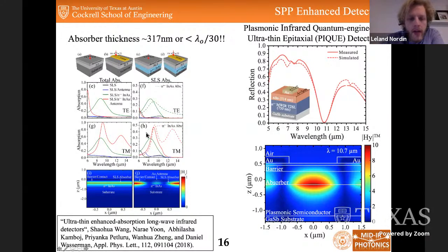And if you look in figure H here, this solid red curve is the simulated absorption in that active region, and it's around 50% long wavelength light and only about a 300 nanometer absorber. So much, much smaller than the diffraction limit, about lambda over 30. So we are now working on actually growing and fabricating these detectors, and we've also now given them a fancy name, Plasmonic Infrared Quantum Engineered Ultra Thin Epitaxial Detectors, or PIQUE.